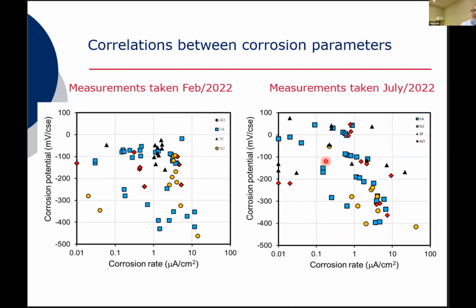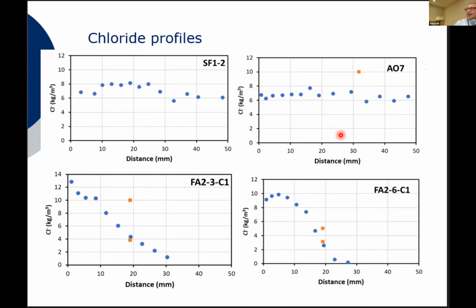There are situations where you can have relatively positive potential and low corrosion current, as expected, but in other cases, at that same low or no potential, you observe situations where the corrosion current density is ongoing. And that might be because the area that is corroding is polarized by the area not corroding, and that's why we observe these more positive potentials.